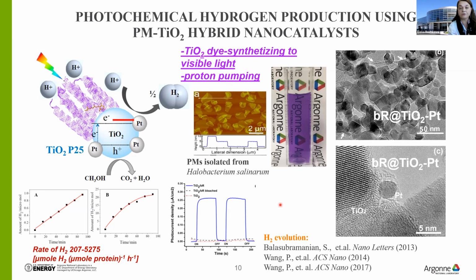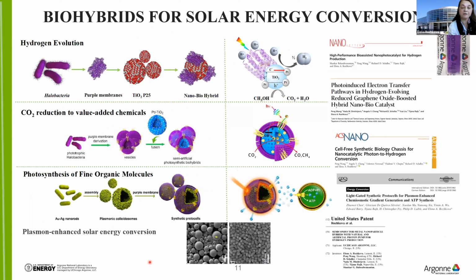It's very important to mention that the system works at ambient conditions in water at room temperature and neutral pH, and also utilizes sacrificial electron donors. After we completed a series of these works, we varied different components. We included some carbon materials. We studied electron transfer. We decided to try something more than just hydrogen production. In this case, we needed to switch from just a co-assembly of titanium dioxide clusters to more sophisticated systems with controllable structures. One work I would like to mention, we completed work on photosynthesis of fine organic molecules like ATP, using plasmon enhanced solar energy conversion with plasmon nanoparticles.